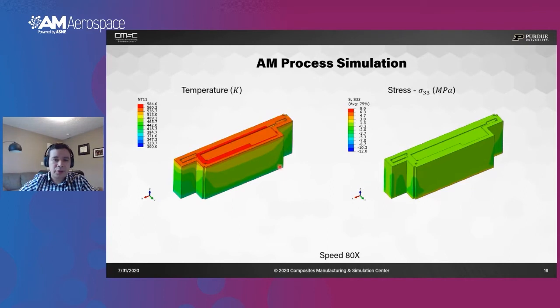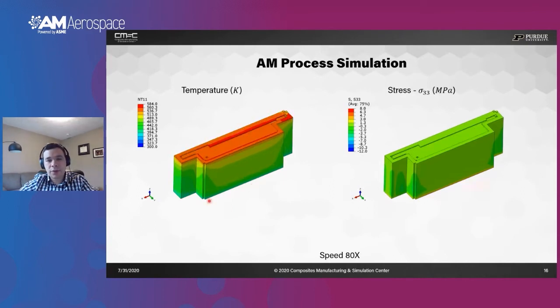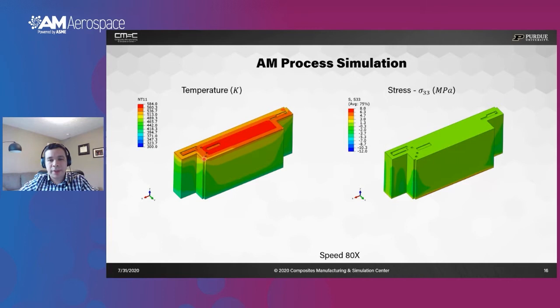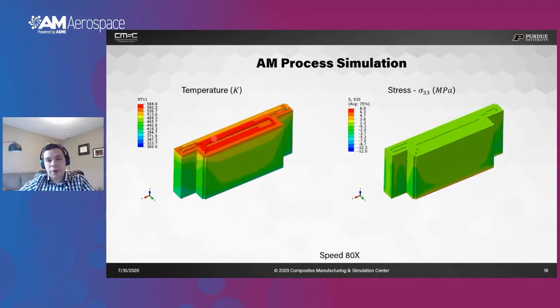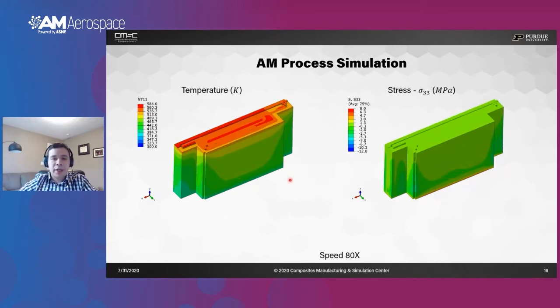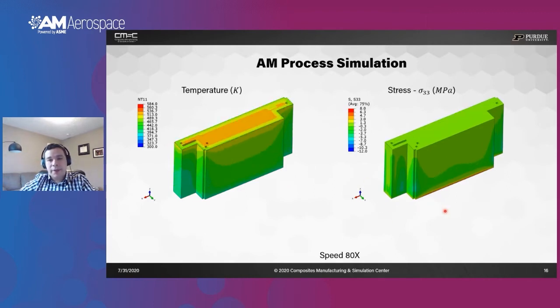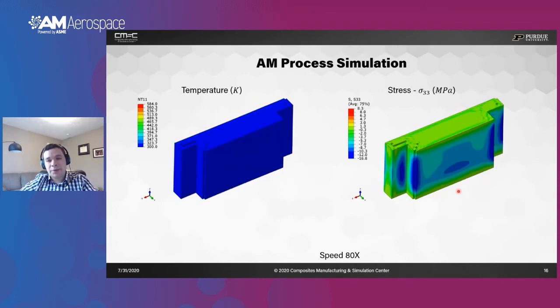We can see here in temperature, the process is highly non-isothermal. The bottom is cooler than the top, and the material cools down as it is deposited layer by layer. Those temperature gradients lead to residual stresses, as well as anisotropy of the printed material. We can see some stresses developing at the bottom. Then once the part is released from the build plate, some stresses also develop. And then upon cooling to room temperature, a different stress state develops. But mostly it's under compressive stresses, which is not really critical for this application.